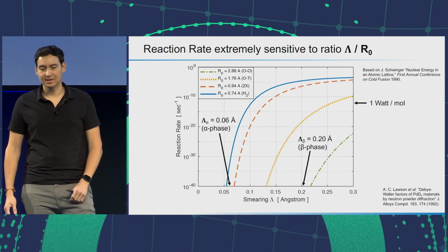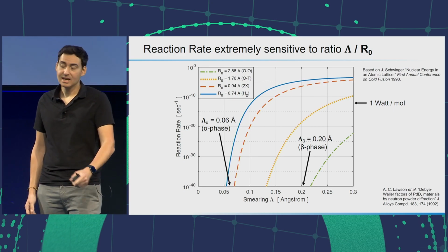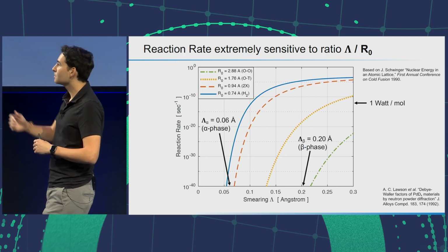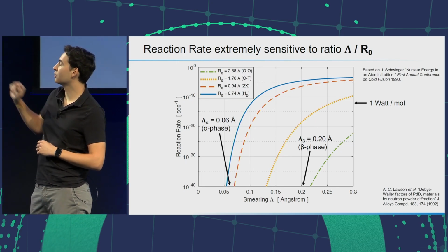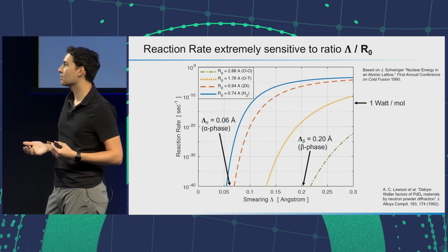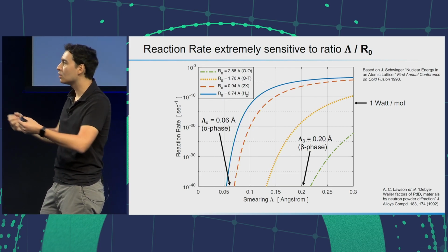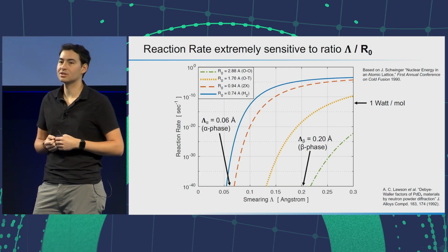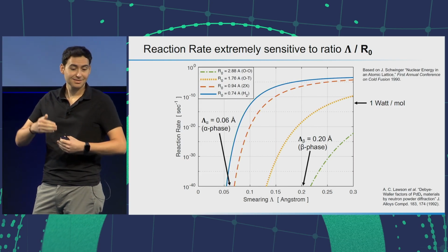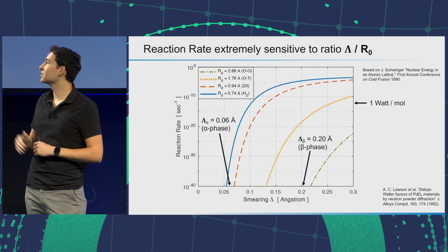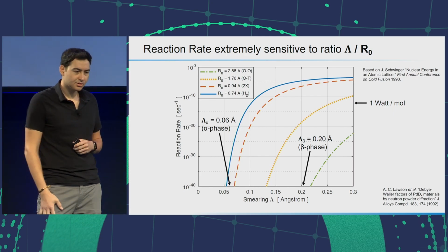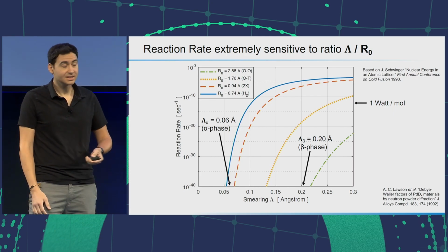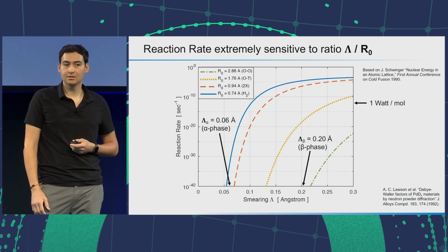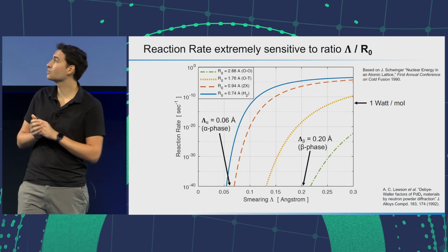But if we were to interpret this at face value, what you would notice is that even at 0.3 of this smearing, we're still below the threshold for the green line. And so that would even suggest going to a one-to-one loading, filling up all of the octahedral sites, is still insufficient to generate heat. So you need to kick your system or get out of equilibrium to cross that threshold. So that was an interesting result that really struck me from the early days, and I think provides some guidance on engineering systems by maximizing this ratio of lambda over R naught.